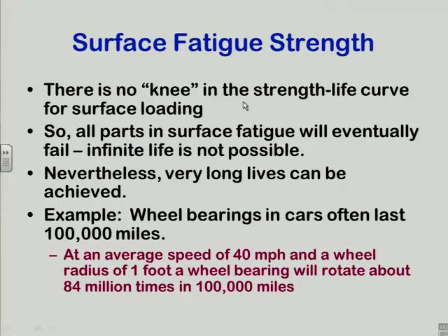There's no knee in the curve for surface fatigue. That's the bad news. Unlike our bending situation, where for steel at least, and titanium, we have this nice flattening of the curve of the SN diagram, so if I stay below that, it's never going to fail, we don't have that advantage with surface fatigue. Eventually, everything succumbs to this failure mechanism. So if I protect my parts against breakage, against all other possible nasty things that might happen to it, and I run it long enough, it's going to fatigue fail in the surface, if there is surface contact.